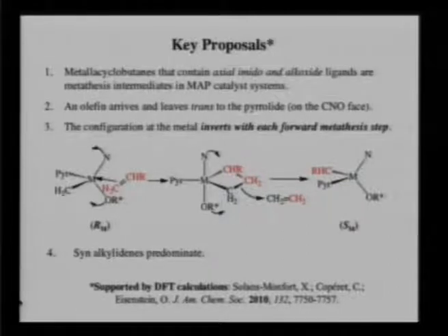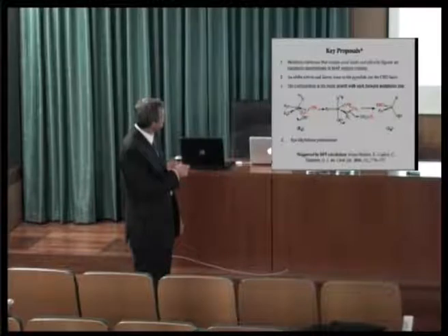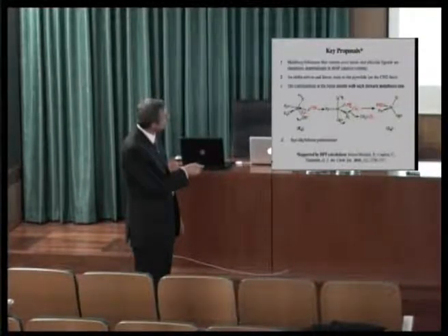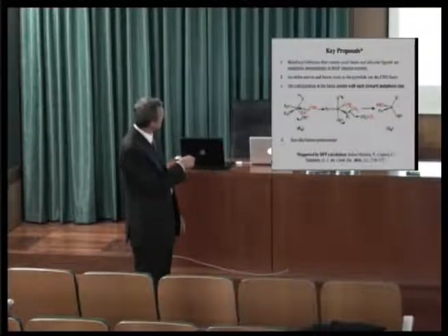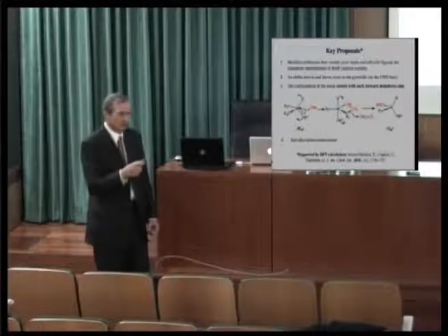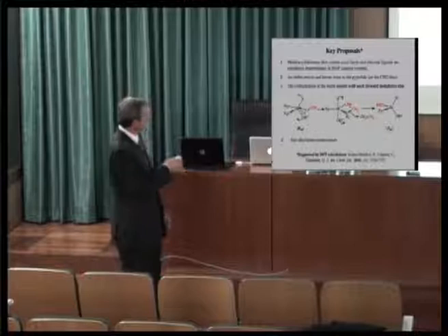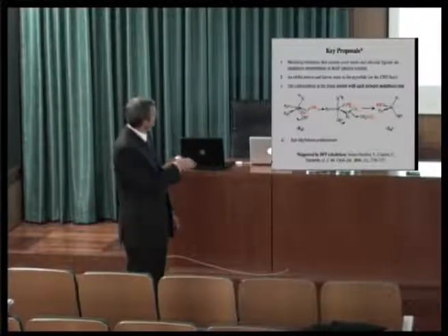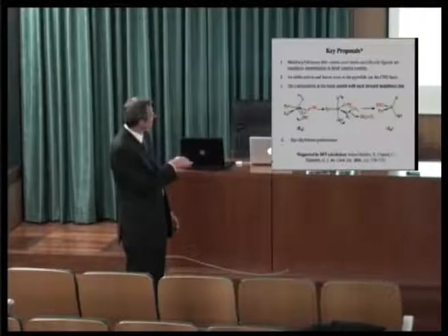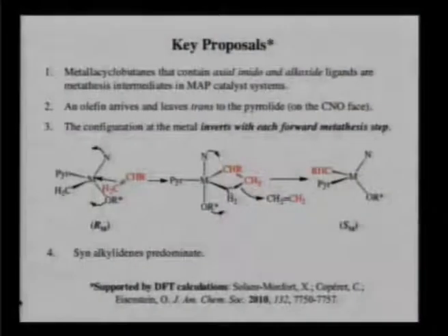An olefin arrives trans to this pyrrolide on the imido-alkylidene oxygen face, and it makes a metallocycle, which then forms product, and the alkylidene migrates around to the back to form the new alkylidene. In the process, you invert the configuration at the metal from R, which is what is shown here, to S. That's a requirement for all reactions involving the metathesis reaction itself. And all of this is supported by DFT calculations by Odile Eisenstein in collaboration with Christophe Copéret, now at the ETH.